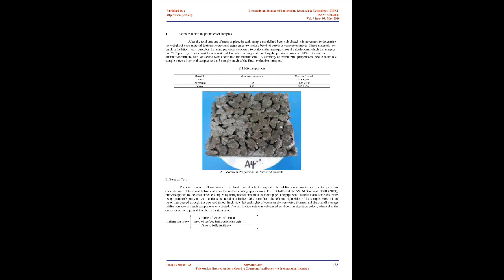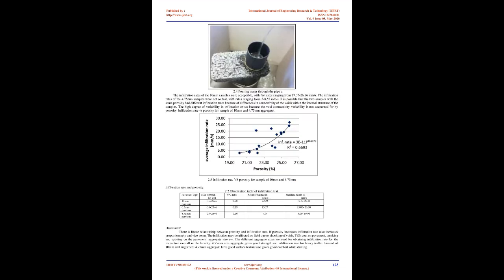The test followed the ASTM standard C1701, 2009, but was applied to the smaller scale samples by using a smaller 4-inch diameter pipe. The pipe was attached to the sample surface using plumber's putty at 2 locations, centered at 3 inches, 76.2 mm, from the left and right sides of the sample. 2000 ml of water was poured through the pipe and timed. Each side, left and right, of each sample was tested 3 times, and the overall average infiltration rate for each sample was calculated. The infiltration rate was calculated as shown in the equation below, where d is the diameter of the pipe and t is the infiltration time. 2.4 Pouring water through the pipe A.